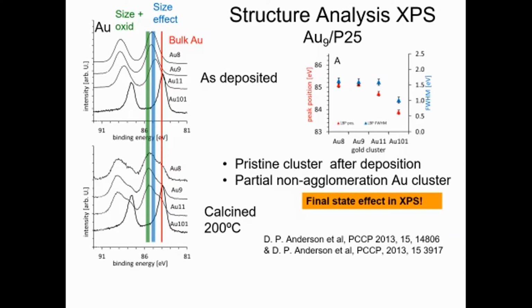On the gold peak itself, for bulk gold, the binding energy is usually 84 electron volts, while we saw a shift of this 84 to a higher binding energy, and this is related to the final state effect of every single cluster. Once we get to 86 and above, this is oxidation and a chemical shift, but we are not reaching the chemical shift; we are seeing the size dependence in XPS, and this is how you interpret it, as different sizes behave differently in XPS itself.